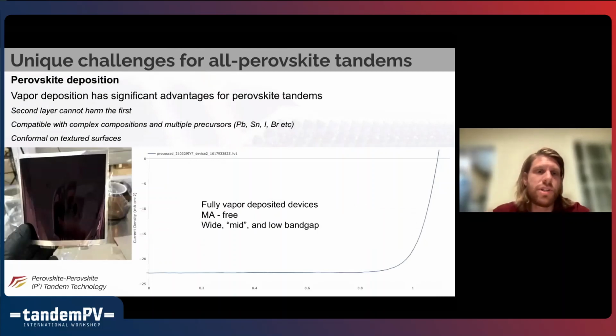So on the deposition front, at Swift, we've chosen to go with a solvent-free approach. So we're doing all our layers via vapor deposition. There's, of course, many different ways that you can deposit materials via vapor. I won't say exactly which techniques we're using, but we've had some very nice results with this. We're able to make the normal mid band gap single junction type materials, wider band gap materials, and low band gap materials, all via this technique. So we've had success in incorporating multiple different precursors, and of course all our materials are methylammonium free from a stability